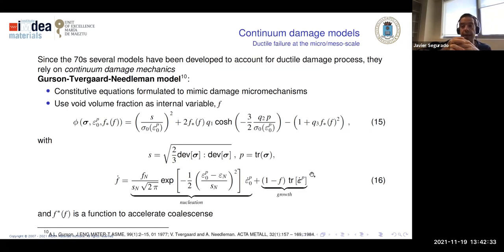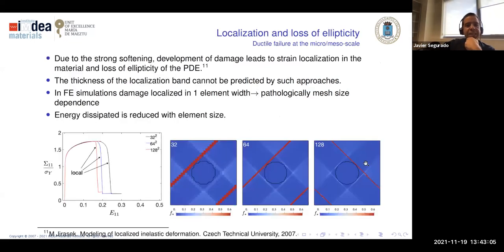So if we have an initial void, the plastic deformation around the void does not produce changes of volume, but it accommodates the change of the size of the void. So it's just saying that the volumetric part of the plastic deformation, that in a standard model is 0 in standard plasticity, here is accounting for the void growth. Well, it's very fast to explain this model, but this is the idea.